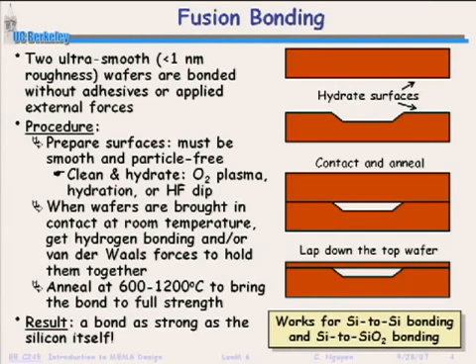And so how is this done? Well, this is done through a process called fusion bonding. There are many different types of bonding processes that I'll talk about. Fusion bonding is when you take two ultra-smooth wafers. The roughness has to be very small, less than a nanometer, in order for this to work well. And you bond them without adhesives or without even applying external forces. So if your wafers have this kind of roughness, you clean them, give them O2 plasma, hydration, or do an HF dip, so that you get some OH bonds on the surface, or you have some HF on it, and then you take the two wafers and you put them together.